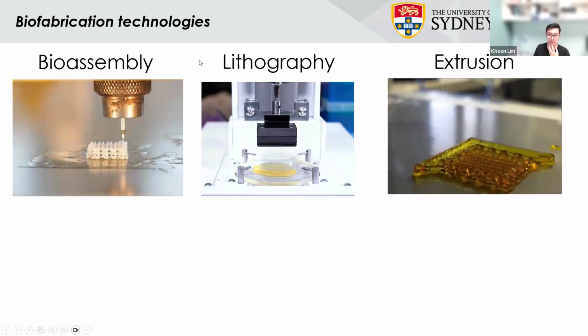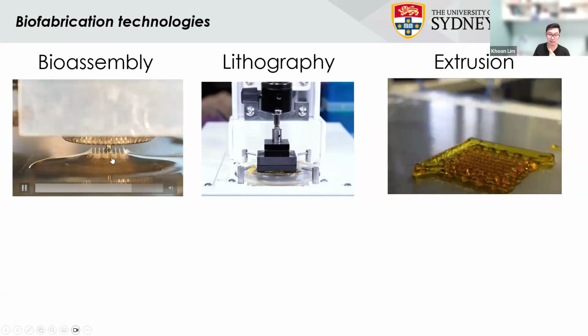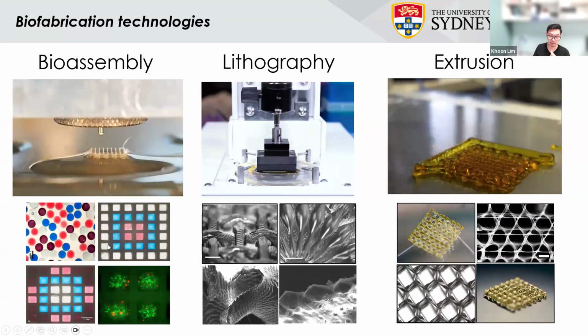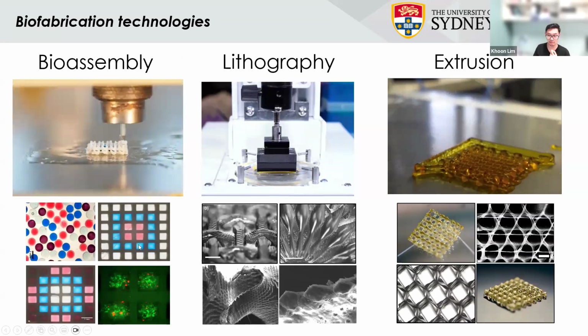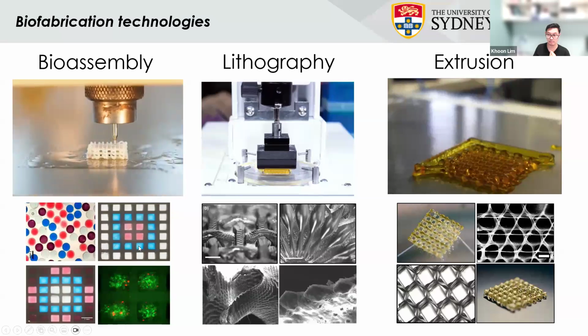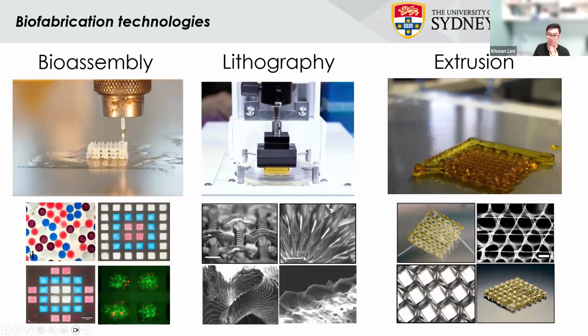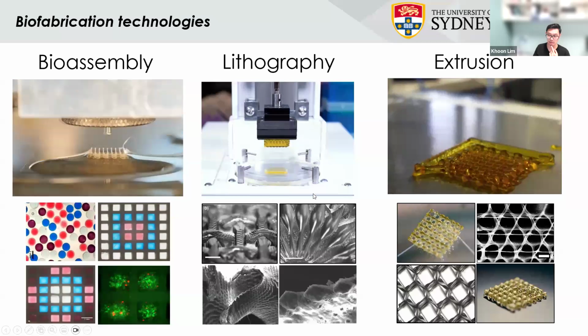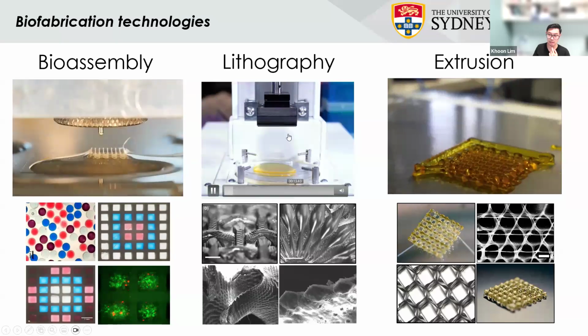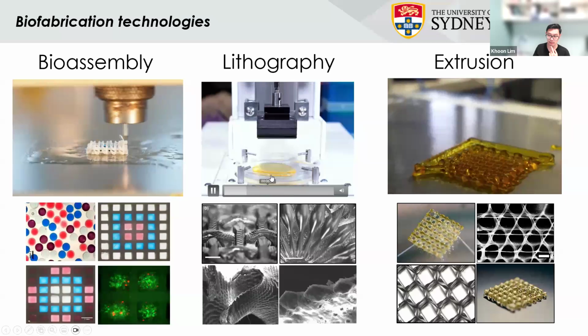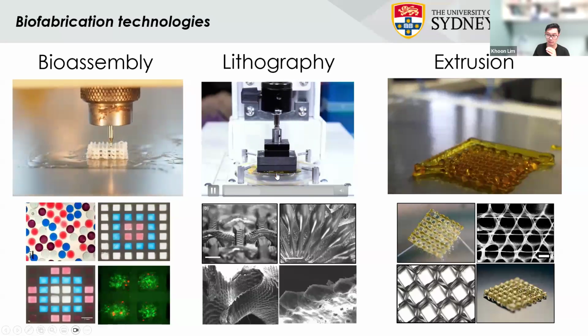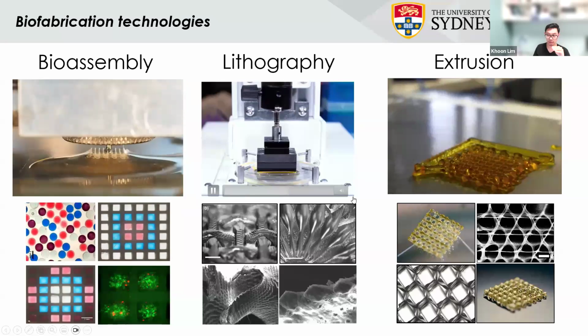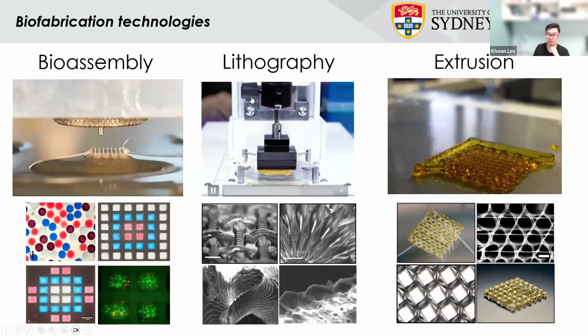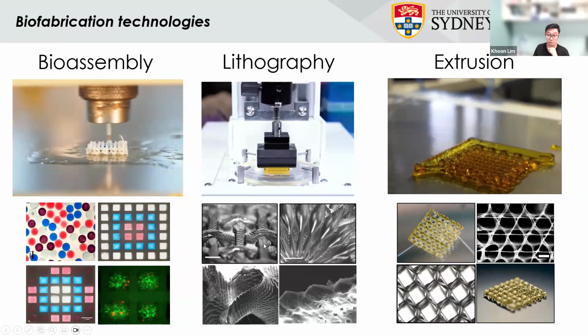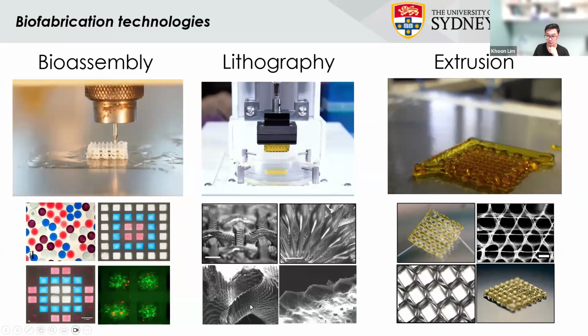So I work with bioassembly a lot. Bioassembly is where you can combine thermoplastics along with hydrogel modules. So you can imagine printing thermoplastics and injecting different hydrogel microspheres within them. We do a lot of lithography work. So lithography where the light actually shines from the bottom. This is your photo cross-linkable material. So if you then have your build plate going down into the bath of your resin and light is shining on them, each time when it's slowly moving up, you're solidifying a layer on top of them. And lithography offers you some unprecedented resolution in this case. You can see really nice structures.